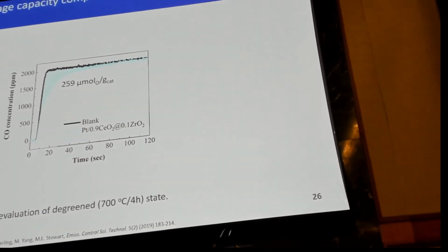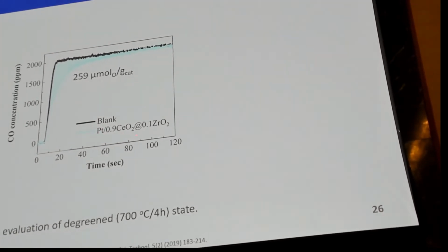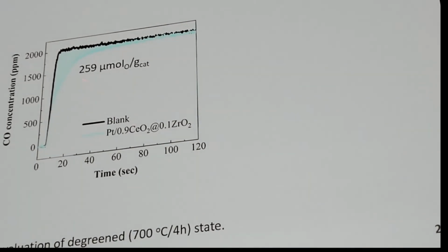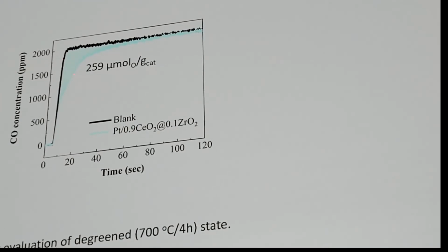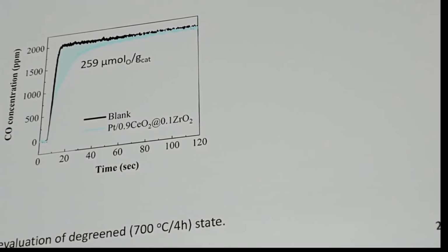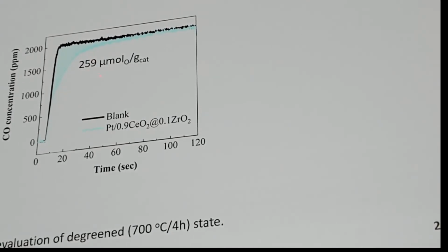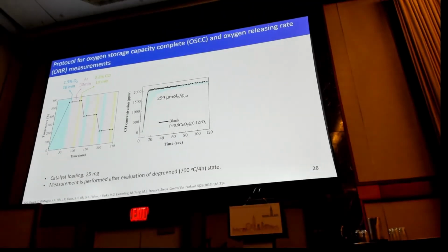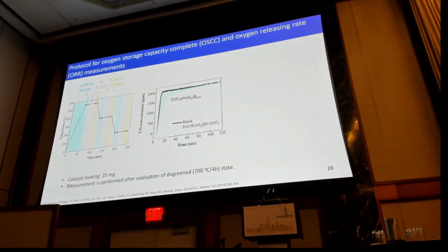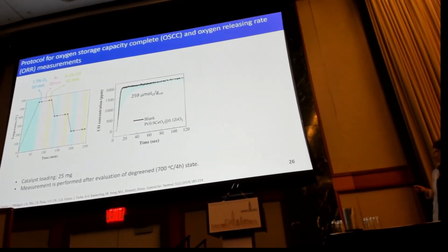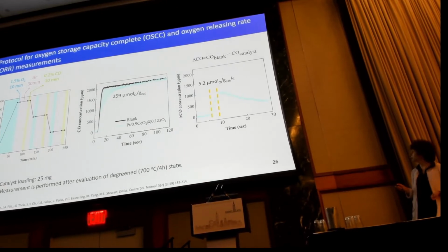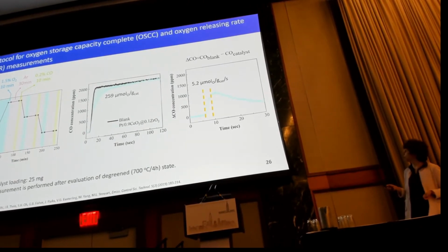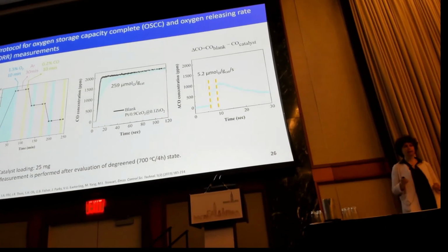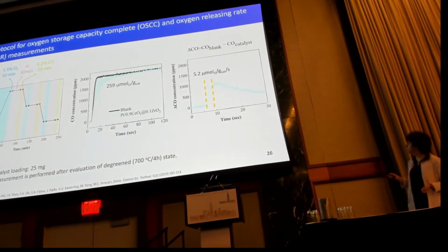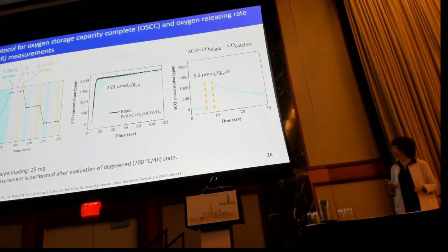And then the light blue line is the CO conversion from the platinum supported on the ceria-zirconia catalyst. So we really see that CO is converted over this catalyst, and by integrating the area between these two curves, we can find the oxygen storage capacity. In this case, it's around 259 micromoles of O per gram of catalyst. If we subtract the CO concentration of the catalyst from the CO concentration of the blank reactor, we get basically the delta CO, and we can find the slope, and this slope gives us the oxygen releasing rate. That's how we calculate the oxygen releasing rate, and in this case it's 5.2 micromoles of O per gram of catalyst per second.